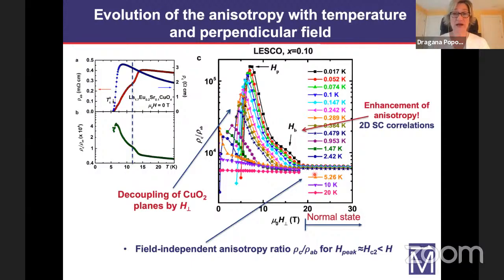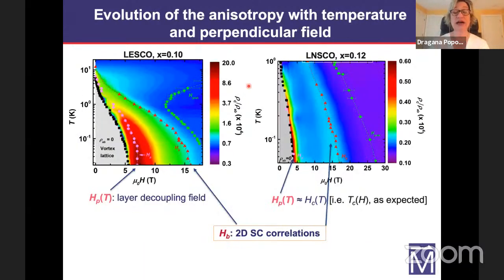These same data are shown here on the left. The color map represents this anisotropy ratio. And here we have some familiar data points from our vortex phase diagram. In particular, black symbols are values of Tc. Green symbols are the positions of the peak in the magnetoresistance that we identified with the upper critical field. So indeed, you can see that as we reduce the field below the upper critical field, the anisotropy ratio starts to increase. It's enhanced around this field where we see a bump in these 2D plots. And in addition, we also have these pink symbols that represent the layer decoupling field. You can see a huge enhancement of the anisotropy there.